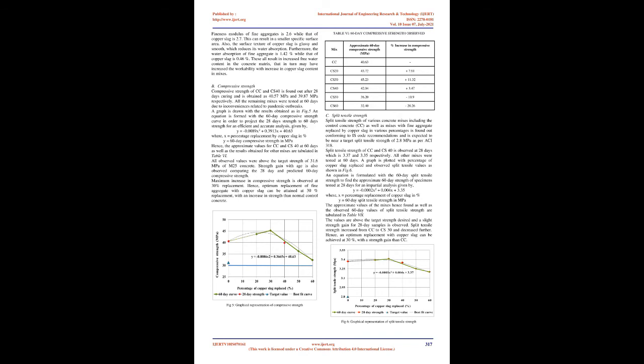Hence, the approximate values for CC and CS40 at 60 days, as well as the results obtained for other mixes, are tabulated in Table 6. All observed values were above the target strength of 31.6 MPa of M25 concrete.